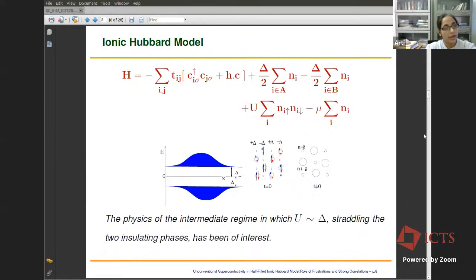The interesting question is what happens when the two energy scales, the staggered potential and the Hubbard interaction, are comparable to each other. And there have been lots of studies on the ionic Hubbard model in the past using dynamical mean field theory, determinantal quantum Monte Carlo, coherent potential approximation, etc., in various dimensions, mainly in the intermediate correlation regime. And all of these studies have basically indicated the presence of some kind of conducting phases, correlated metals and magnetically ordered metallic and half metallic phases in the intermediate regime of this model.